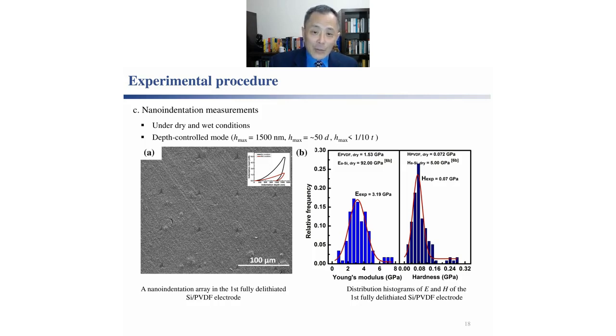The indentation was quite deep, about 1500 nanometers in depth. This will allow us to cover a large number of silicon particles to obtain results of the composites. And because of the random distribution of pores and surface roughnesses, a large number of indents were made on each sample, about 50 to 100 indents. That allows us to produce a histogram of the hardness values and modulus values.